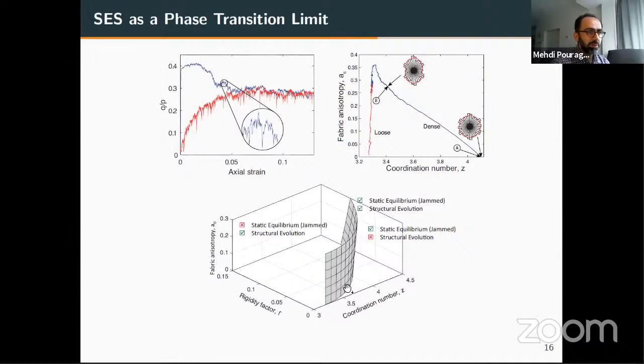Now here, this is the manifold, and the dense material is approaching this from the right-hand side. So we saw that at the very beginning, we do not see much of the structural rearrangement and dissipative deformations. It seems as though the sample is so overdetermined or jammed that statistically it can have equilibrium, but the structure cannot evolve. It has to lose the contacts and approach the isostatic limits so that the structure can evolve.